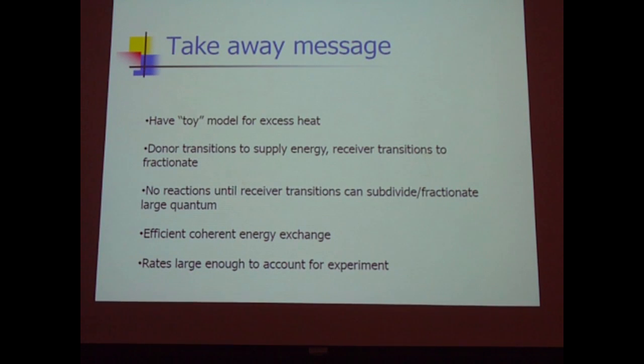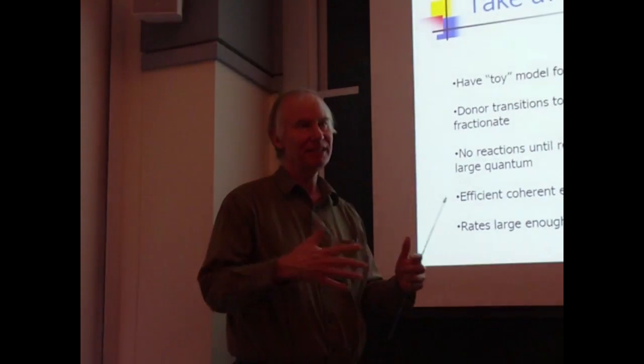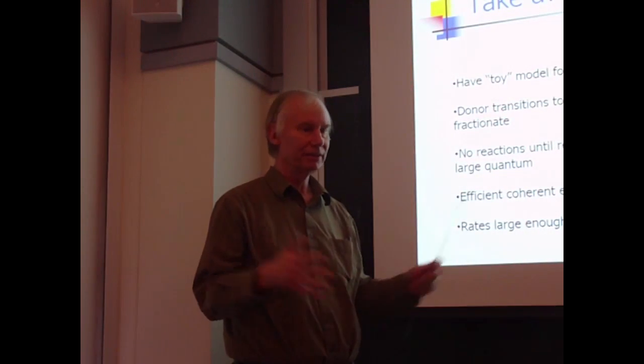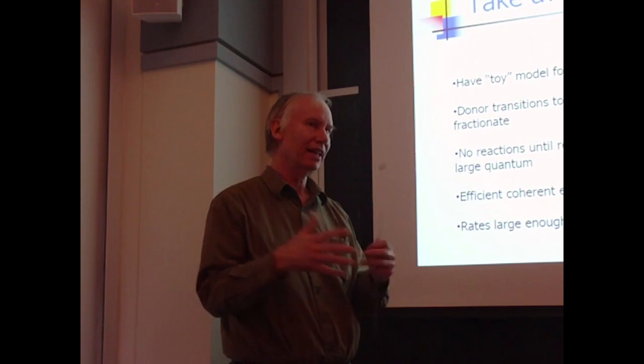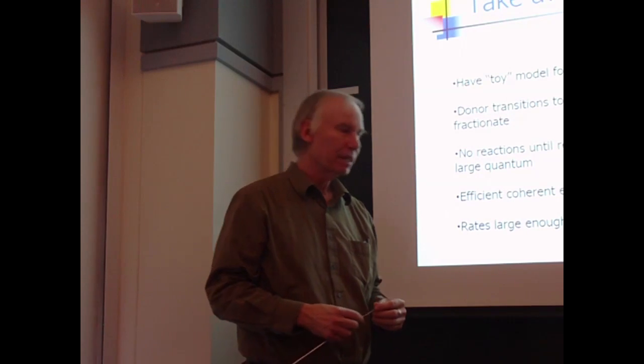I'm trying to get a physical picture of the coupling to the phonon mode. I'm wondering what sort of volume would be necessary to not just have the local material kind of vaporize with 24 MeV if you're coupling to the phonon. Well, in my view, if you've got a localized phonon mode, you're not going to do anything. You can't have enough nuclei coupled to it to make anything work. You have to have a delocalized phonon mode. Right. So you have to have something big vibrating. You have to have coherence in the vibrations over a large... How large are we talking in terms of...